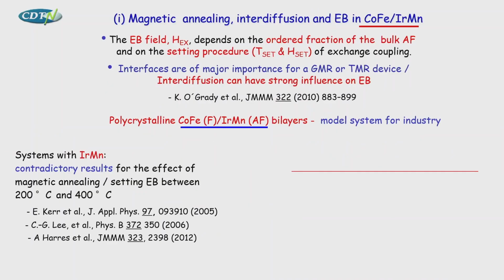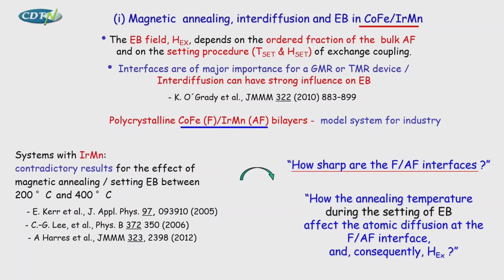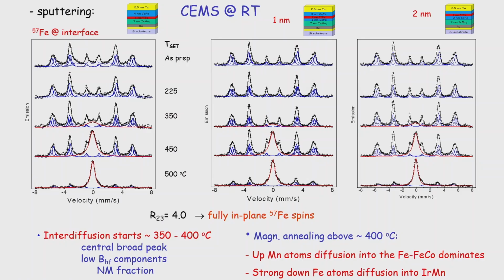Okay, let's say a few words about interdiffusion in this thing, okay? And cobalt iron, iridium manganese is a standard exchange bias system even for the industry. And we want to see how sharp is the interface, because you have to apply annealing under magnetic field to, let's say, improve the coupling in this system, okay? And the idea was to see how sharp is the interface. What happens when you do heat treatment in this sample, okay? And we did the same. We have samples grown by sputtering, putting iron 57, 1 nanometer at different positions. And we did, let's say, the magnetic annealing at different temperatures.